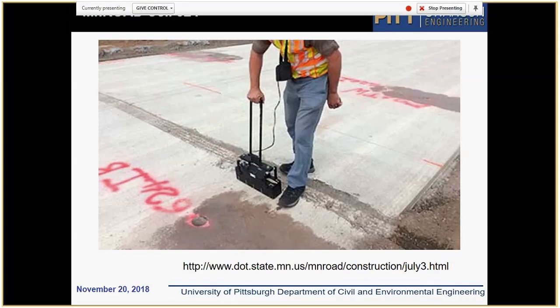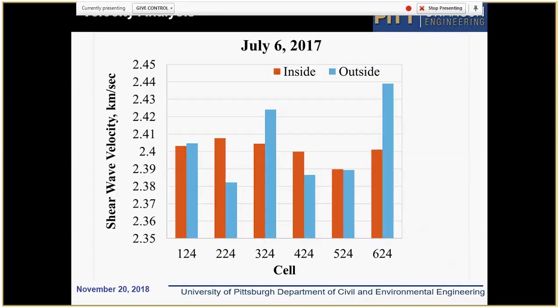We also evaluated ultrasound tomography data collected by Dr. Hoyk for us. And first of all, we evaluated shear wave velocity, and the values we obtained confirm the estimates we got from previous studies, that basically concrete stiffness after 24 hours was where we would expect it to be. Its velocity is about 2.4 kilometers per second, which means that the tensile strength was most likely about 400 plus psi. That corresponds to maturity measurements, and stiffness was about a couple million psi at that time.